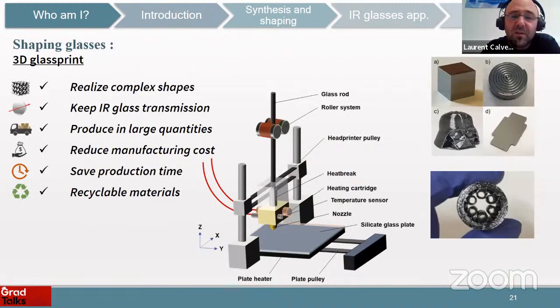This is not the only way to shape the glass. Something we developed, I would say 3-4 years ago, is 3D glass printing. So it's very interesting to print glasses. It's not so easy. It has been developed by the MIT on window glass, but on chalcogenide glass, it's much more difficult because I told you that we don't want to see oxygen in the glass. So we developed some experiments under glove box or under neutral atmosphere to get chalcogenide glasses.